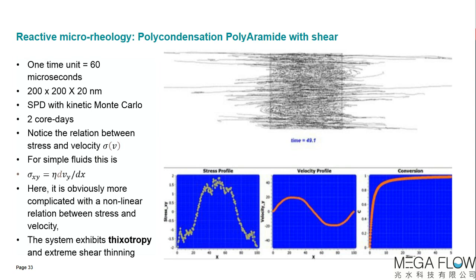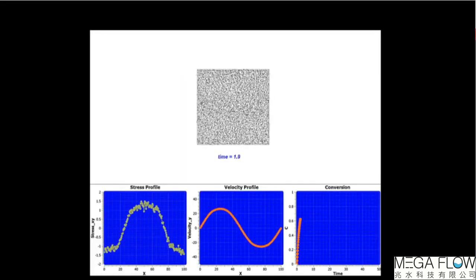This is more or less at the end, so conversion 95, 96% is what you can get with polycondensation. And what you see immediately, for example, here in this region, the velocity profile is very flat, right? Very flat means a low gradient, means a very high viscosity because the stress is not zero. Here, you have a simple gradient, linear slope almost, and then you count it back, and then you have a lower viscosity here. So in principle, from this simulation, one can calculate the viscoelastic response as a function of conversion in one shot. So let's let the video play.